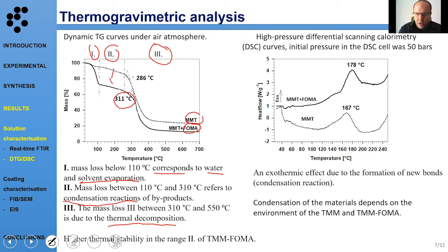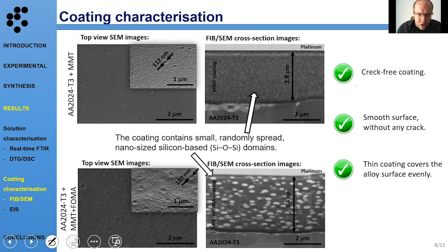Moreover, if we also characterize it by differential scanning calorimetry, we can see that this peak, which is characteristic for condensation, is also shifted to higher temperatures. Here are the top view SEM images of these coatings after deposition on aluminum alloy. So we can see that these coatings are crack-free. They are very smooth and without any cracks. So that means that these coatings cover the aluminum alloy surface evenly.